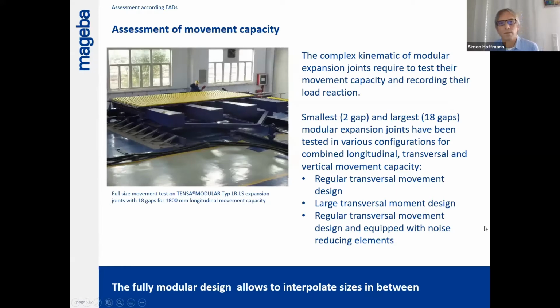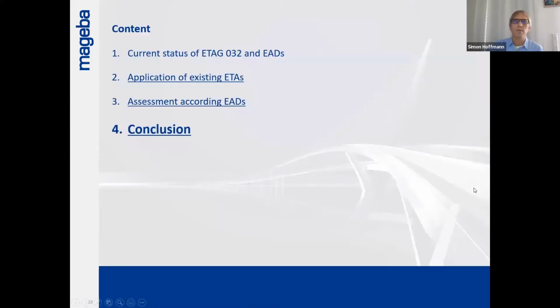One of the most demanding, if it comes to really big joints, is a movement capacity test, as you will need to test modular joints for the largest applicable type covered by the ETA. So this means in our case, in LR18 here with noise reduction sinus plates type LR-LS, with 1800 millimeters of longitudinal movement capacity. Then we tested as well the smallest one, which for a modular joint is one with 2 gaps. The full modular design of our joints allowed us to interpolate in between the sizes. For many other types, you would need to test all single sizes. So let me conclude.